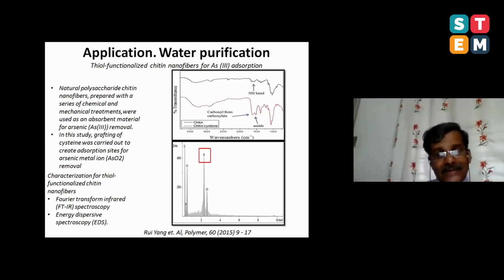And this nanochitin is an exciting material for water purification. I wanted to show you a very nice work of Professor Yang and group. This is the nanochitin made by Professor Yang and group. And what they did is they made a small chemical modification to remove arsenic. And their modification was with a cysteine molecule. Look at this. They modified chitin with a cysteine molecule. And when you do such modification, you can remove arsenic from water.